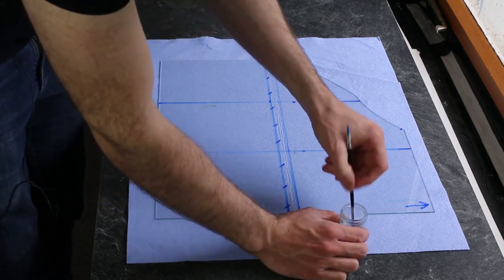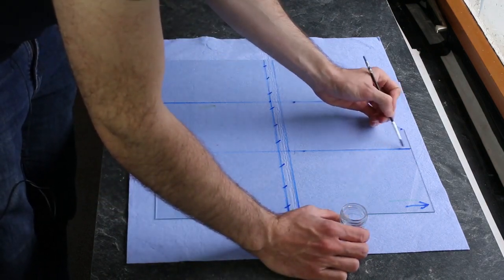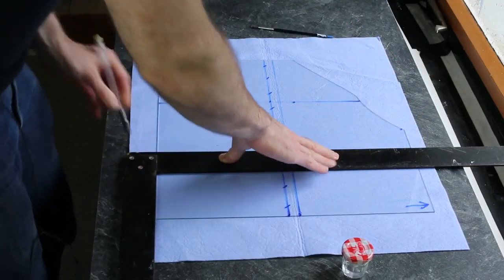I use kerosene and a brush to lubricate the glass at the cut line. I'm using kerosene instead of other oils because it quickly evaporates and leaves little residue. I take a glass cutter and cut the glass in a sweeping motion, applying constant pressure. While cutting, you should hear a clean hissing sound. The cut puts stress on the glass. The kerosene fills the cut and keeps it open. As time passes, the glass heals, so you should break the glass quickly after cutting.